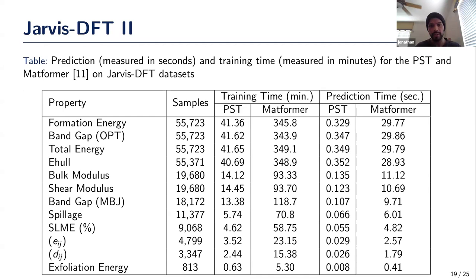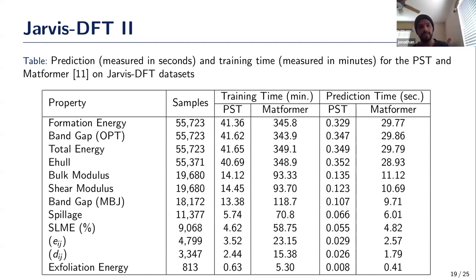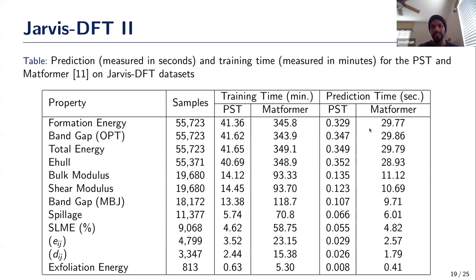Compared to Matformer, because it uses the entirety of the unit cell, all graphs are much larger, and the line graphs are much larger still. Our improvement in training time is around nine times better, and prediction time is vastly better — essentially 100 times faster. This is the prediction time in seconds across the whole test set, around 5,500 samples for formation energy, though some of this can be attributed to implementation efficiency.